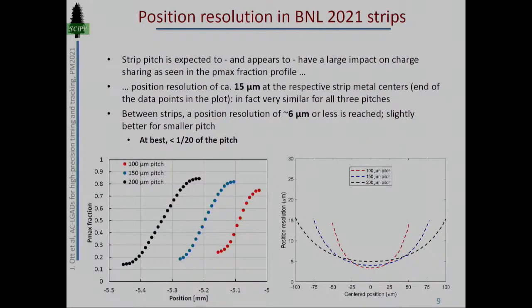Here we see some results from these BNL strips with different pitch. The fraction of the signal on one strip naturally depends on the pitch. When we look at the position resolution finally, the smallest pitch gives the best timing and best position resolution, down to less than 5 microns.